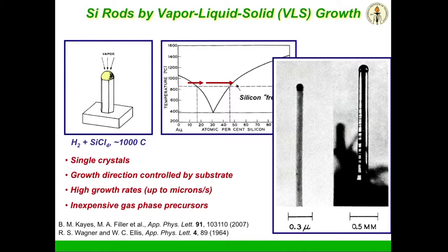Now, this is the poster child of the silicon nanoscience community. You grow such VLS rods, you get a whole bunch of felt because the wires grow everywhere. You ultrasonically remove one. There are over 1,000 papers to do this. You publish it on the cover of Science or Nature and declare victory. On the other hand, none of them are good enough for us for 2 reasons. One, it turns out nano is bad here, micro is good for technical reasons that I'm happy to explain later. But 2, we have to orient all our wires directly toward the sun, and there was no established method to do that. They grew felt everywhere, and you can remove one of those wires, but that's not what we needed.